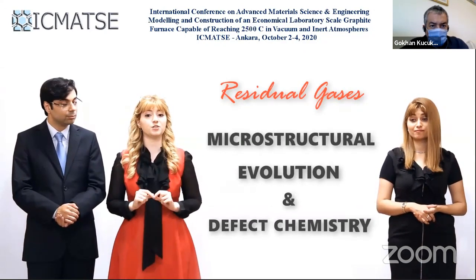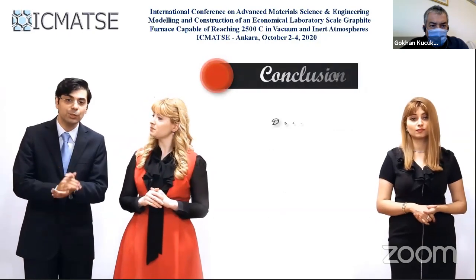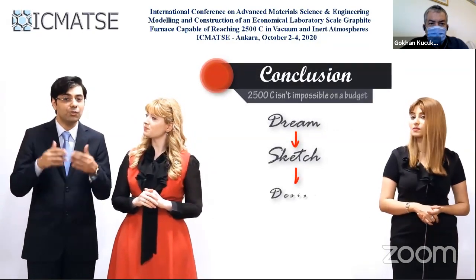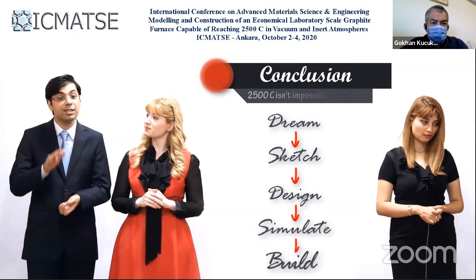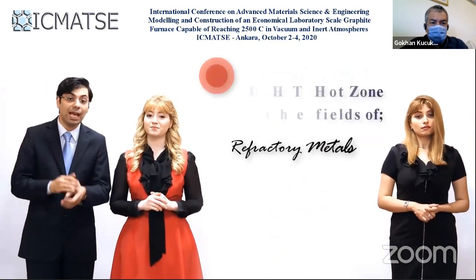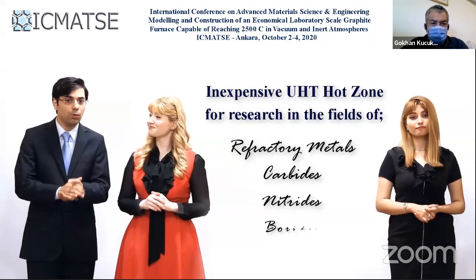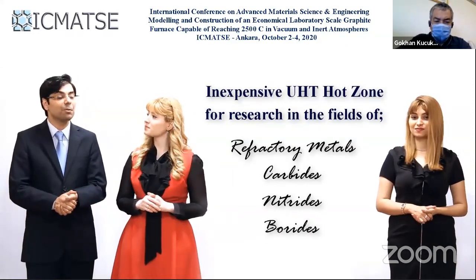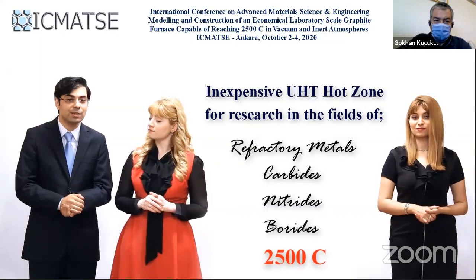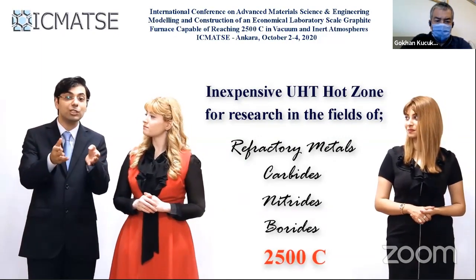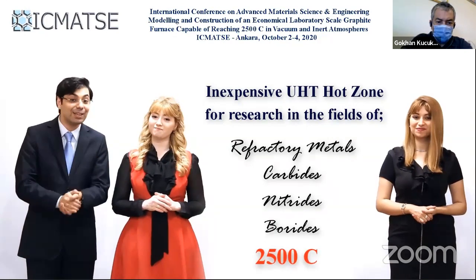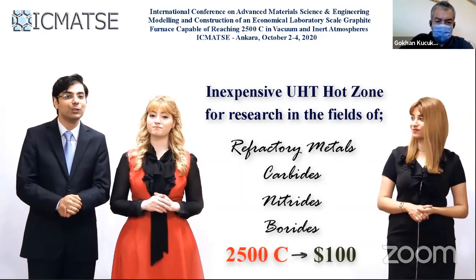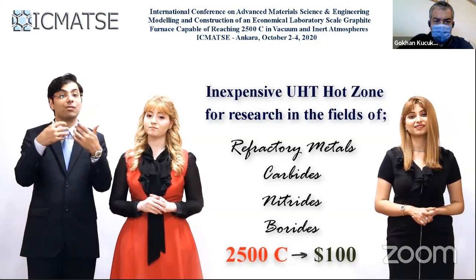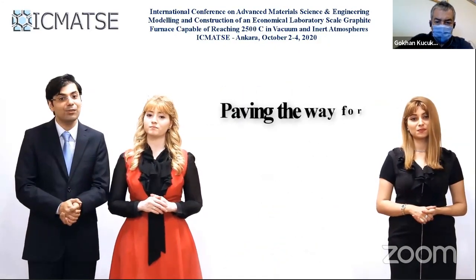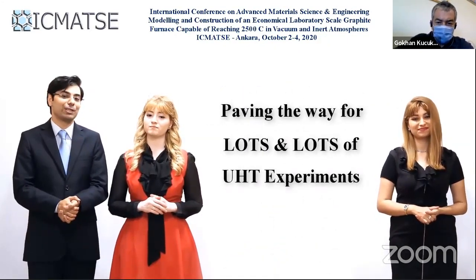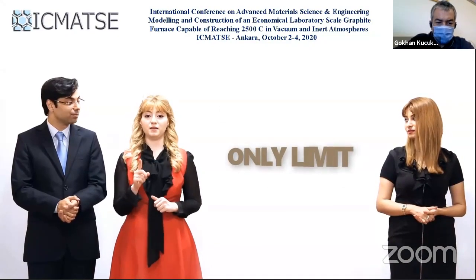the material being researched. So to conclude, every one of us researching in the field of ultra-high temperature materials, especially on refractory metals and their carbides, nitrides, or borides, can build a graphite furnace capable of reaching temperatures up to 2,500 degrees Celsius by bringing together the equipment usually available in most labs and a hot zone of just $100 with the service life of several hundred hours, paving the way for lots and lots of high temperature experiments. With the only limit being our creativity.